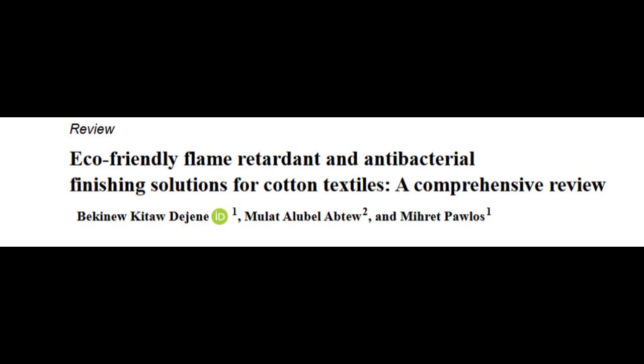A natural booster. Okay, nanomaterials beyond silver. Zinc oxide, ZnO, copper oxide, CuO, titanium dioxide, TiO2 are big ones. Yeah. Also nanofibers, nanocomposites. The key trend here is green synthesis, using plant extracts or microbes to produce the nanoparticles, avoiding harsh chemicals. Like that sumac leaf extract for silver NPs you mentioned. Exactly. In-situ synthesis right on the cotton showed strong antimicrobial and UV protection at low concentrations.